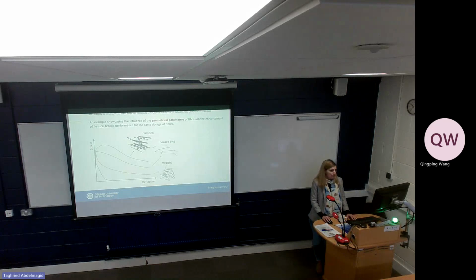And now, what about geometrical parameters of fibers? Here we have the plain concrete. When we have the straight fibers, we can achieve, these three examples are from my research, but in some research we didn't get so much increase of strength of concrete. So let's say we get some strength increase, and then for the straight fibers there is no hardening phase. There is nothing going on. So in truth, these fibers we are adding are quite okay, but with no great improvements.